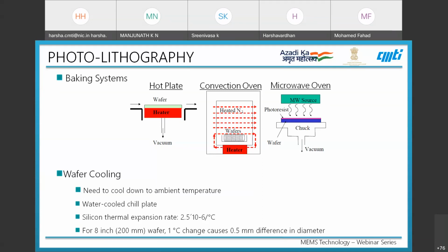After the soft bake, the cooling of this wafer is also equally important. We need to cool down the wafer after the soft bake process to ambient temperature. We can either do a natural cooling, or we can use a water-cooled chill plate to have the cool down done, because the silicon thermal expansion rate is at 2.5 times 10 power minus 6.